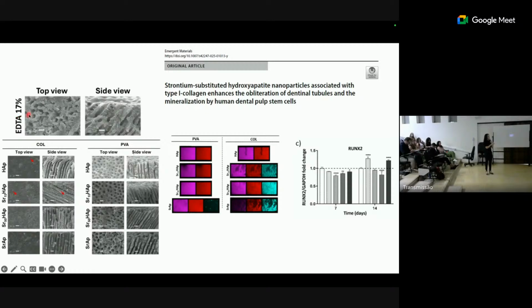Here, I show you the treatment of eroded dentin. In this case, the dentin was eroded using EDTA. And here, we treated the eroded dentin with collagen and hydroxyapatite containing strontium. And here, the same particles, but we used PVA mimetic gel. And if we see here, the gels with collagen were much more efficient in coating dentin compared to the PVA gel. These particles were also able to induce differentiation of the stem cells in a mineralizing phenotype.